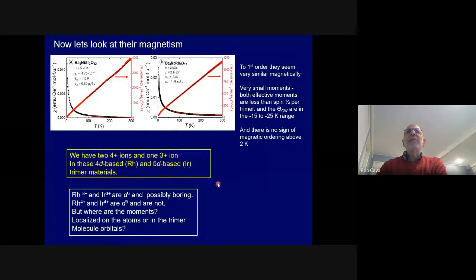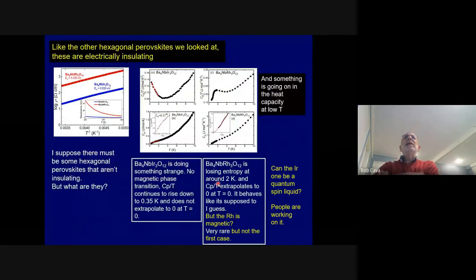So let's see what happens at even lower temperature. At even lower temperature, it's possible to measure the heat capacity of things. So here's the heat capacity of the niobium iridium 3 O 12 and the niobium rhodium 3 O 12. You can see that the rhodium one seems to magnetically order at around 1.8 Kelvin.